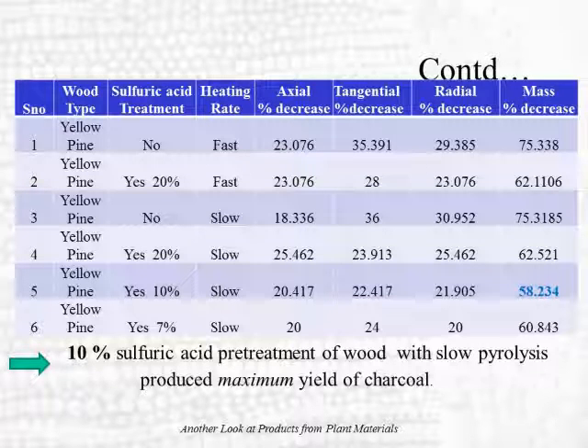Okay, so you can use, I guess, standard distillation methods that might be used in petrochemical industries, such as catalysts, or what this student set out to do was look at a pretreatment of wood with sulfuric acid, where sulfuric acid will essentially begin the degradation of the polymers at room temperature. And so there's a lot of information on this, and I apologize for putting such a table up there, but the bottom line that we got from the series of tests that were conducted is that you can